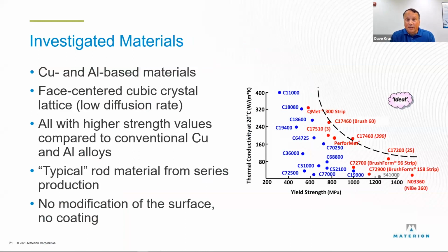So just to go into the materials again very quickly, why we're looking at these materials and related to hydrogen. They're all copper and aluminum based. They're face-centered cubic, and the reason I talk about that is that's the lattice structure. Body-centered cubic, which is a steel structure, tends to absorb hydrogen more quickly than face-centered cubic. They all have higher strength values than traditional alloys, and these are right out of production, and we haven't done anything to the surface. If you called us and wanted to put something to test, you bought material from us or one of our distributors, this is exactly what you would get.